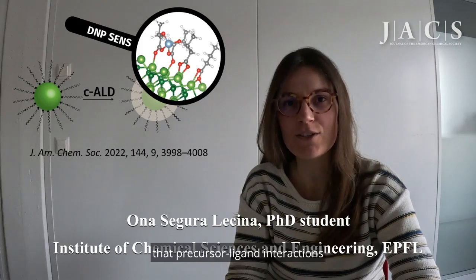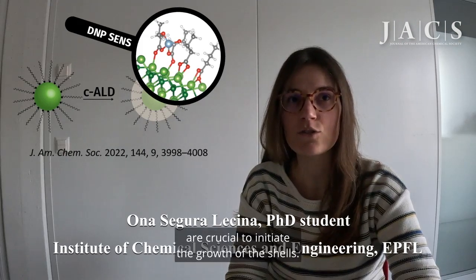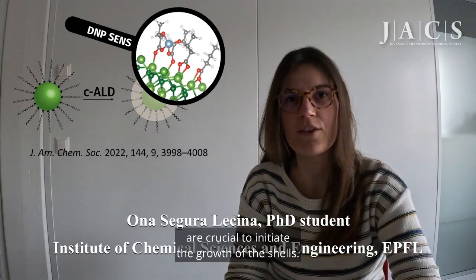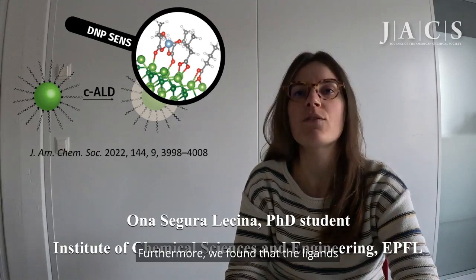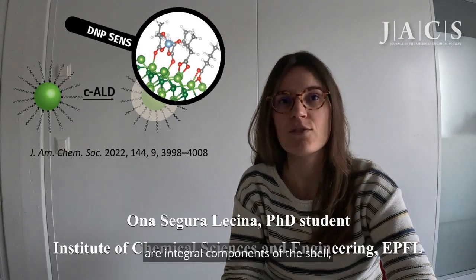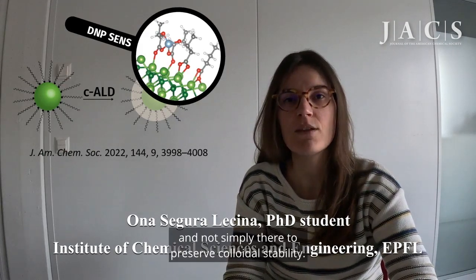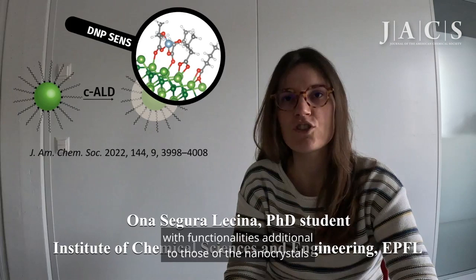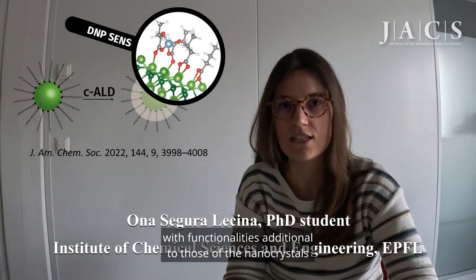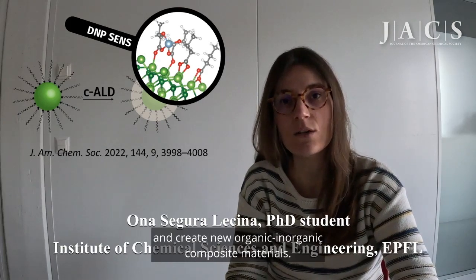Our experiments revealed that precursor-ligand interactions are crucial to initiate the growth of the shells. Furthermore, we found that the ligands are integral components of the shell and not simply there to preserve colloidal stability. Thus, we sought to leverage this unique feature of our shells to introduce ligands with functionalities additional to those of the nanocrystals and create new organic-inorganic composite materials.